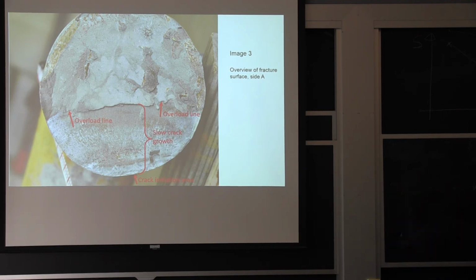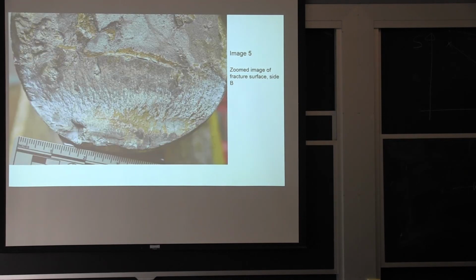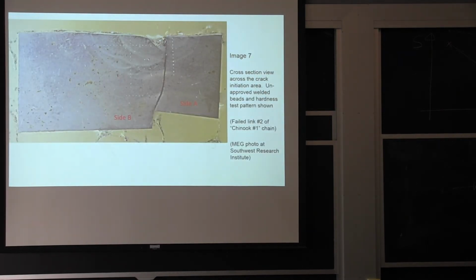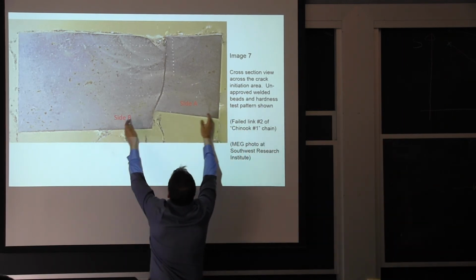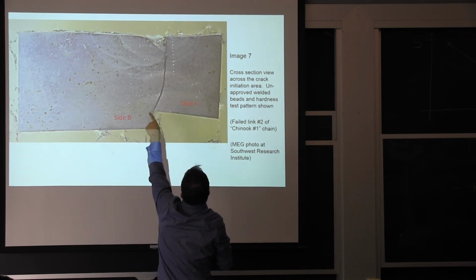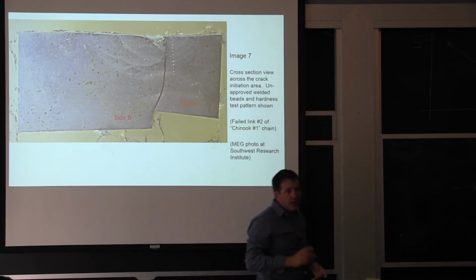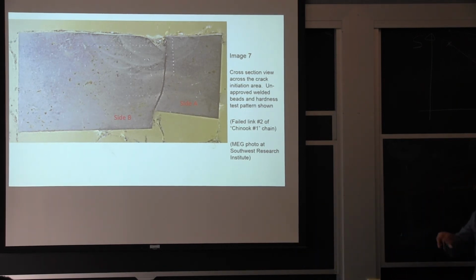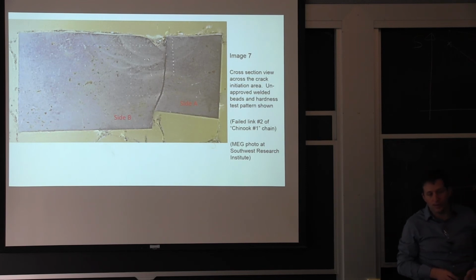The reason for the cracking is after they did the shop fabrication, the shop fabrication was essentially the big flash weld. They had a problem, and they went back and did repair welding. So the little lines that you see there are individual passes of welding that they did after the flash welding. And what really happened there is your cooling rate is much faster, and therefore you have a hardness that exceeded the threshold to start having small cracks forming under the seawater and the cathodic protection.